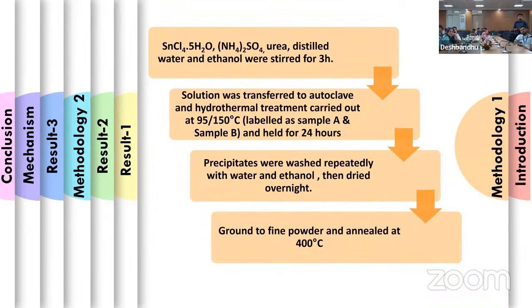So the methodology we adopted for preparation was that we first took a mixture of tin, ammonium sulfate, and urea with water and ethanol and stirred for 3 hours. Then the solution was transferred into an autoclave, and the hydrothermal treatment was done at two different temperatures, 95 degrees Celsius and 150 degrees Celsius, which were labeled as sample A and sample B, and then kept for 24 hours. The precipitates obtained were washed repeatedly with water and ethanol and then dried overnight, and then they were ground to fine powder and annealed at 400 degrees Celsius.